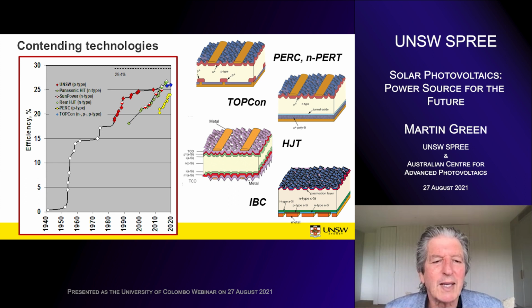But in the 1980s, our group started having some success in improving efficiency. So we're the red dots there. We took the efficiency from about 17% up to 25%. So about a 50% improvement in a technology that already had about 40 years prior development. So we're quite proud of that effort. But there were 4 cell structures. So we got to 25% at the turn of this century, 25% efficiency.